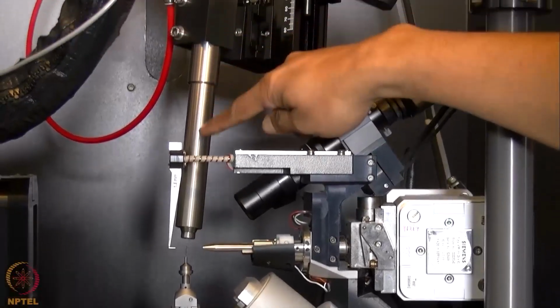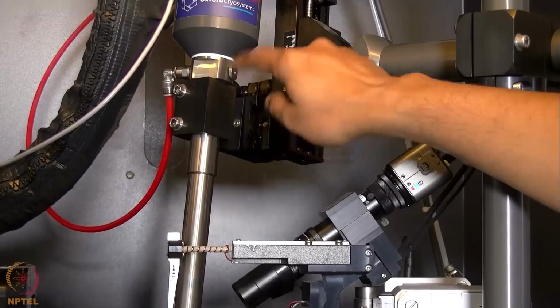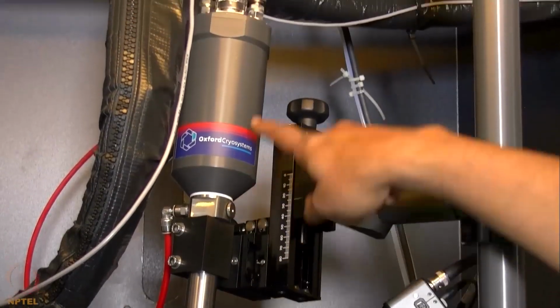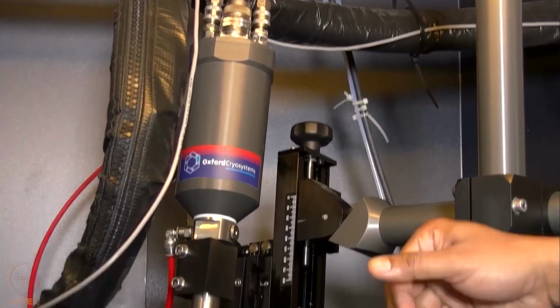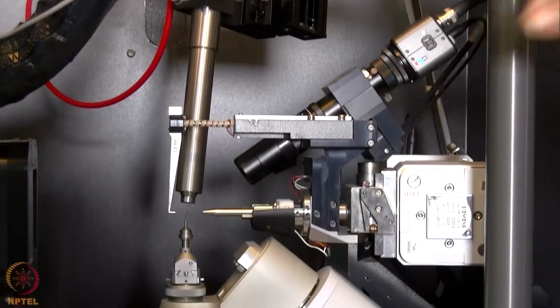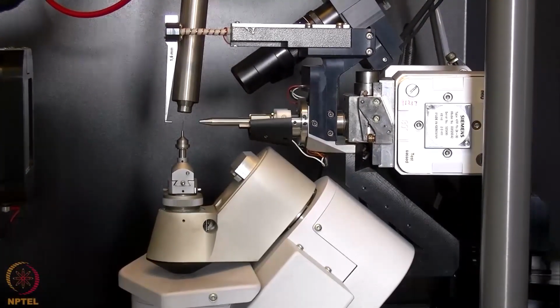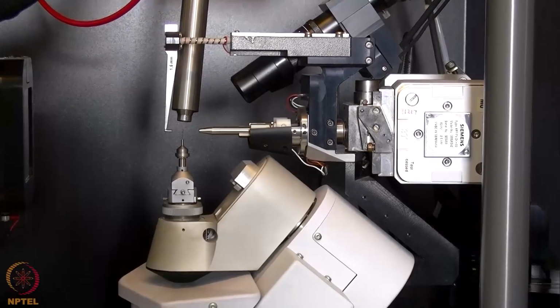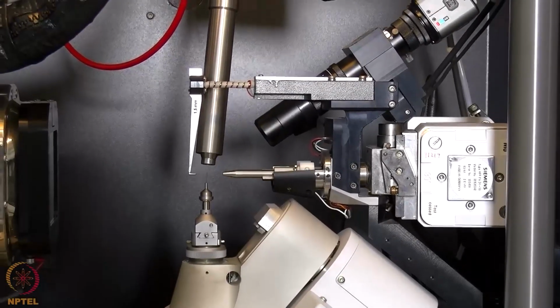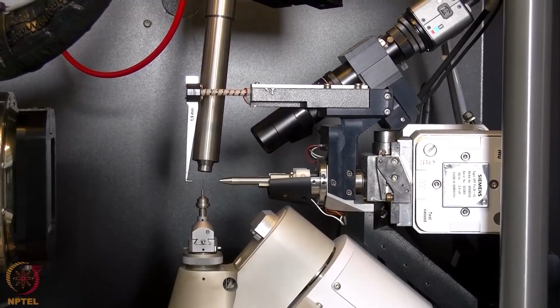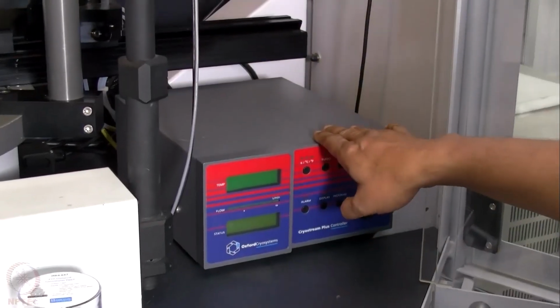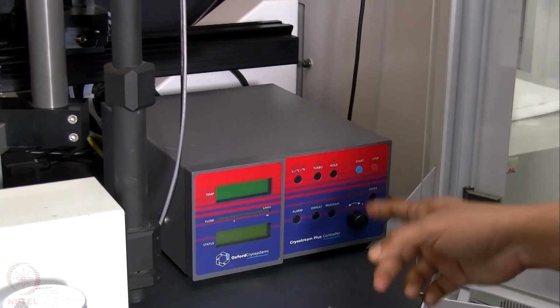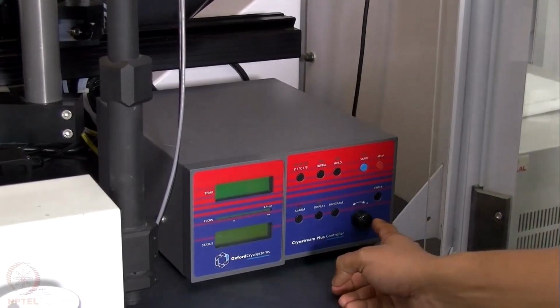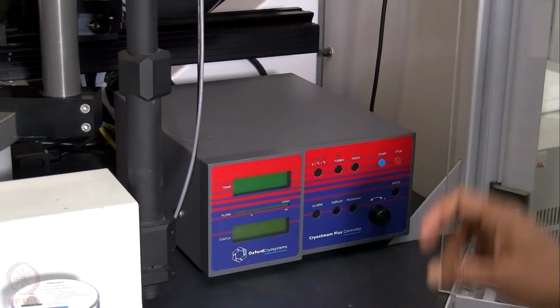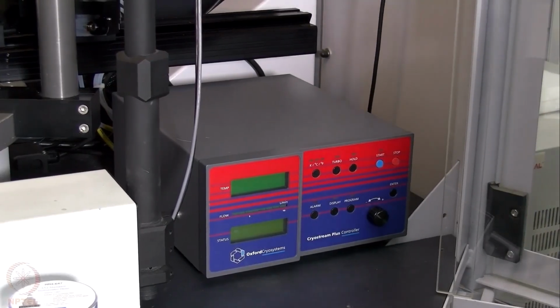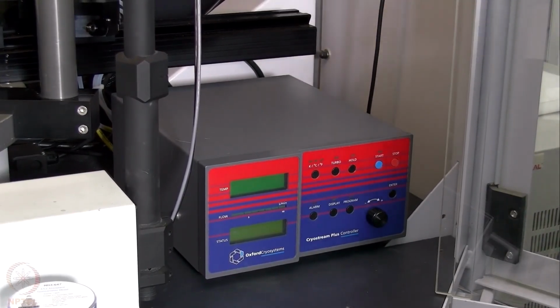Here we have the cryo head of Oxford cryo system that you can see. This Oxford cryo system helps us to cool the crystal to a very low temperature. We can go as low as 100 Kelvin using liquid nitrogen as coolant and collect data at 100 Kelvin temperature. This is the cryo controller for the cryo system that can be operated either using these knobs or using a software, so that we can reduce the temperature in a desired rate.